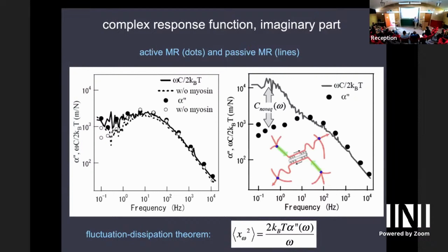We have a high ATP concentration, which is a technical issue with motors. If you have high ATP and fairly small aggregates of myosin, they're what's called non-processive. So they can't hang on, they can't produce large displacements. But when the ATP runs down, then what's called the duty ratio of the motors goes up, and then they can actually hang on and start pulling. And we also did that, of course, with low ATP concentration to begin with, but then you have to stabilize it. So it's all technical details.